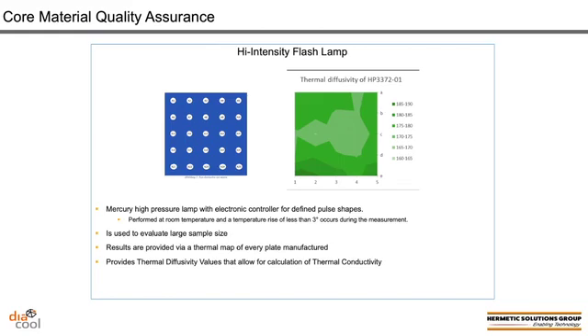So by taking this essential thermal map of this material, we can tell how uniform the material is distributed, how well the material has coalesced. And we can look at this with an eye to creating materials that are uniform in nature and have good distribution of thermal conductivity across a substrate that's as large as 150 millimeters square.